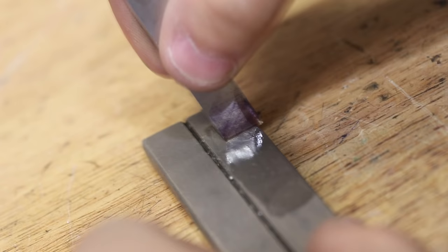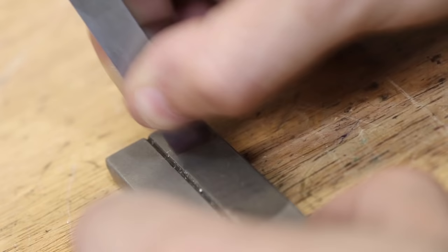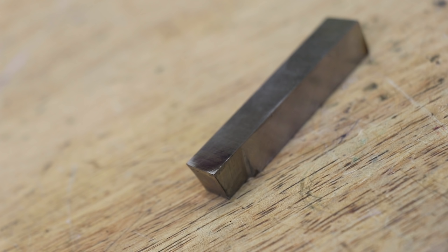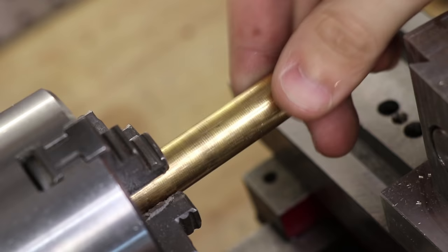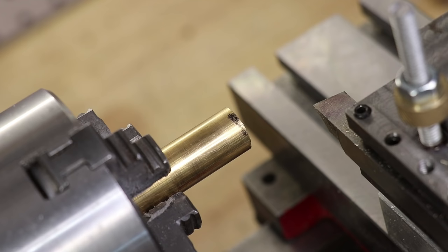Before we do anything else, we'll need to hone the tool. The grinding wheel leaves a bit of a burr which we need to remove. I like to use a diamond lap, but you can always use a whetstone if you want. And believe it or not, that's our first cutting tool done. This one here is set up to cut brass and bronze. Brass and bronze are very odd materials to work with. If you use a sharp cutting tool with brass, the tool tends to grab into the workpiece. It can actually dig into the workpiece and ruin it. So let's take a test cut.